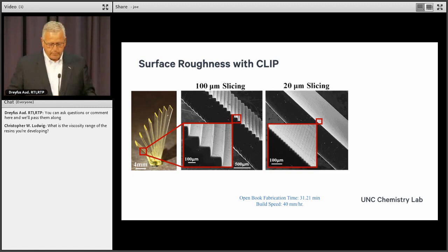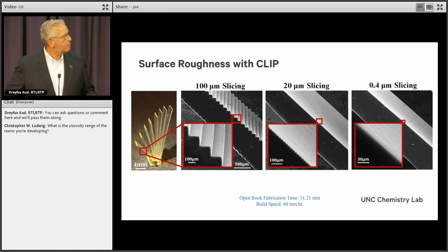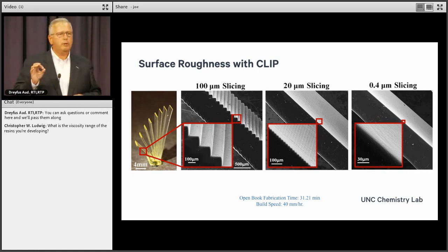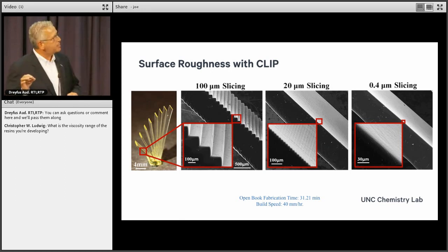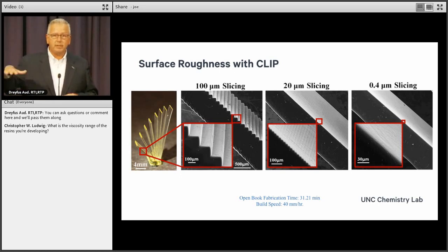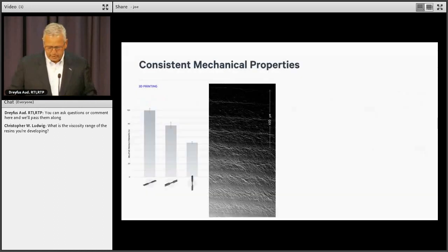But she could have switched it every 20 microns in Z, right? Or every 0.4 microns in Z. And you see what happens to the surface finish, right? This is a continuous production of this part. If this were a traditional 3D printing over and over again, and you went from 100 micron slices to 1 micron slice, you would slow it down by a factor of 100, right? But while we grow these parts, they're all grown at the same speed, that we're just image processing, which we can do very quickly. And that allows you to have these kinds of surface finishes.